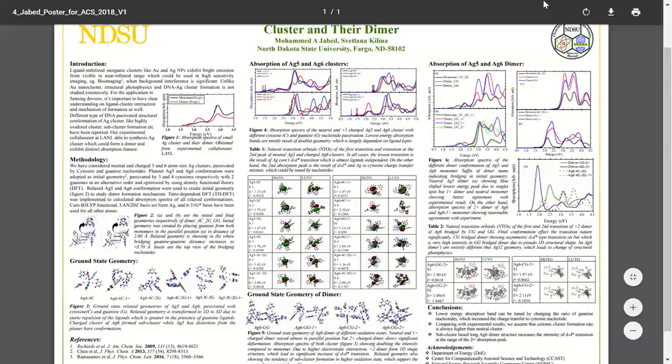And if you look at the absorption spectra, this is the experimental absorption spectra. The red line is showing the absorption spectra of the dimer, and the black line is the monomer. They saw that whatever the size of this cluster, when they form the dimer, the lowest energy peak is going to diminish and become a dark peak, the second absorption peak increases in intensity specifically, and the third one is going to lower intensity than the monomer in that case. So we started with these experimental results.